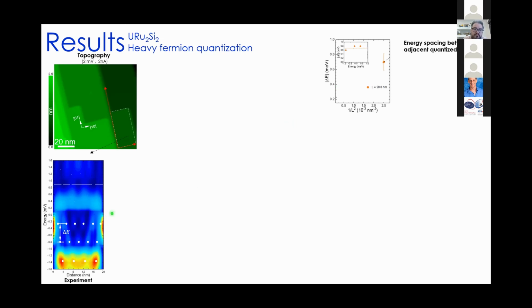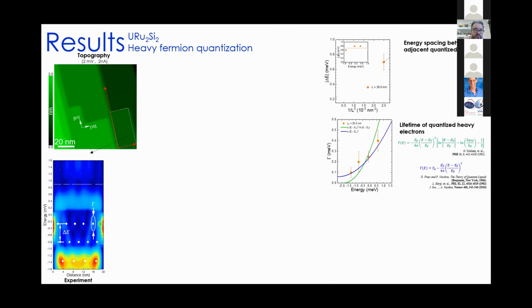We also know that by measuring the energy widths of the quantized resonances, we can get information about the scattering properties of the electrons. This energy level broadening, which we call gamma, is related to the lifetime of the quantum states. In this case, again just for this terrace, we represent it in orange, and the green line represents the behavior of a perfect two-dimensional electron gas without interactions with the bulk. The blue line is the predicted behavior for a Fermi liquid theory, and it includes the inelastic electron scattering with the electrons from the bulk. As you can see, the blue curve fits our experimental data better, which means that we have more contribution of the bulk electrons to the surface.